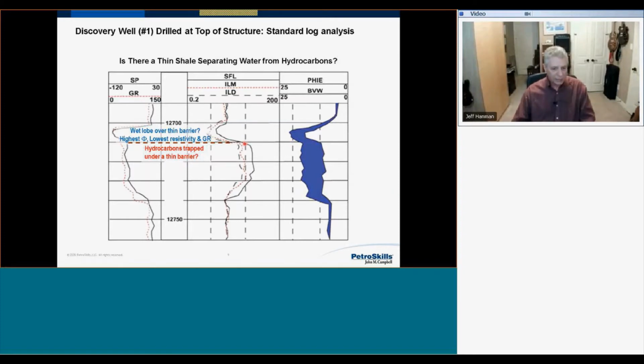And then something happens. We have this dashed line that separates this lower resistivity interval from a higher resistivity interval. We do see that the gamma ray is higher, the SP has less deflection than it does in the upper lobe, and the porosity is diminished from the upper lobe. So could this dashed line actually represent a thin shale layer? Is this upper lobe really water saturated?